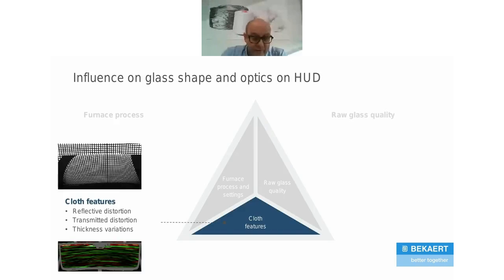Another thing is the cloth. What kind of cloth can you use to improve the bending process and the glass quality in the bending process? What is important to mention is that the cloth will press your glass and will be in contact with your glass. It will also create some local thickness variations in your glass. Very minor, on a scale of microns and not millimeters, but it will have a very big impact on the reflective distortion, the transmitted distortion, and also the thickness variation.